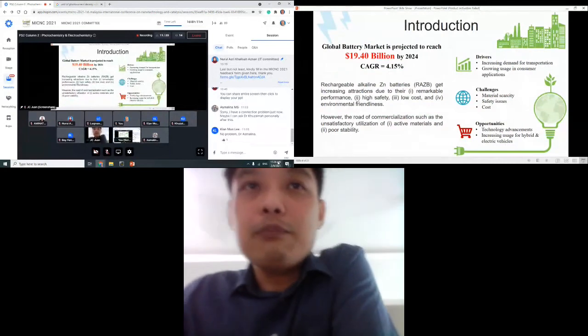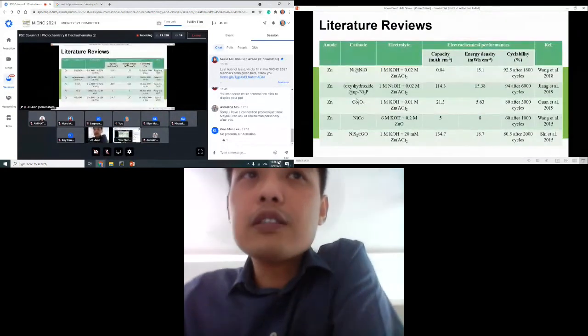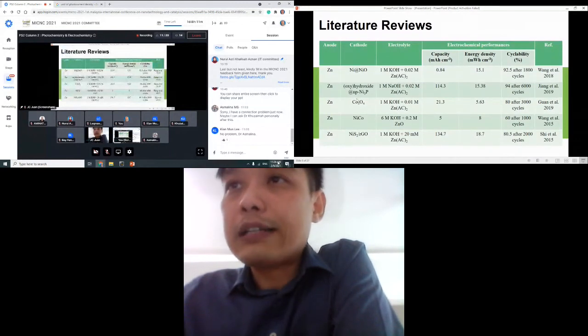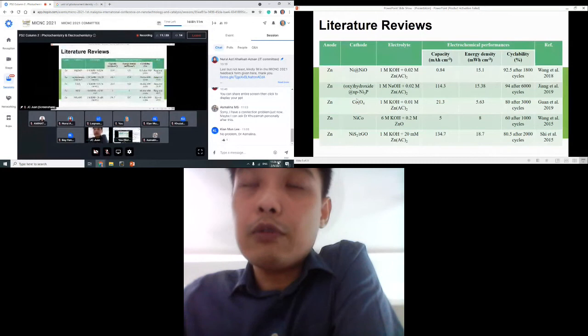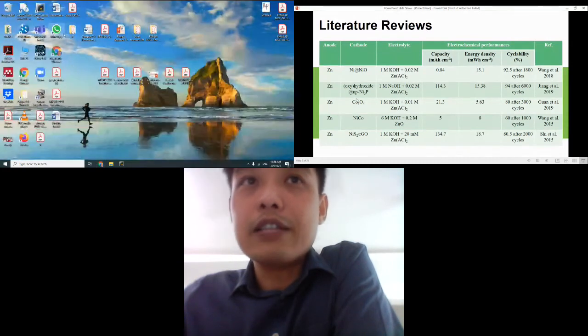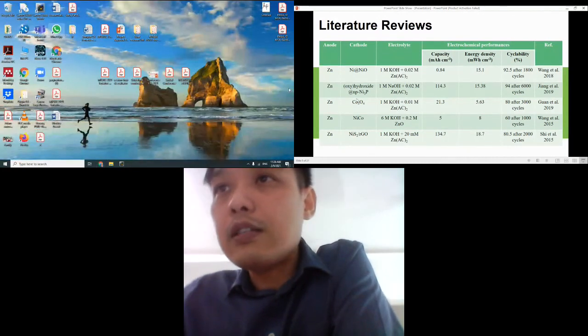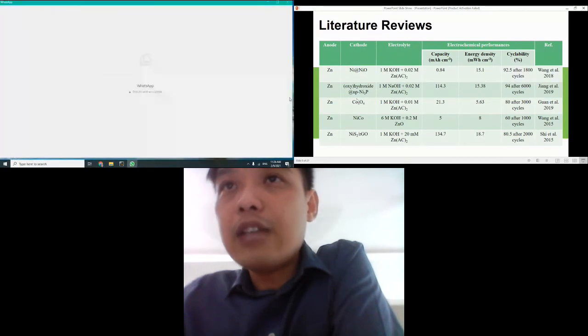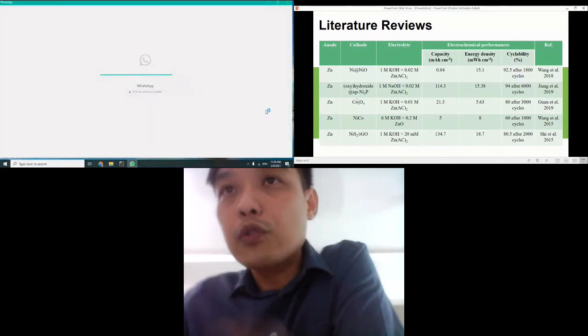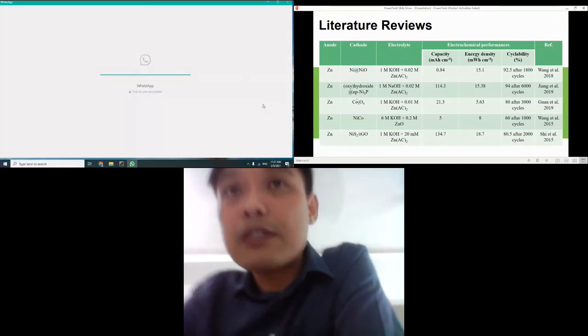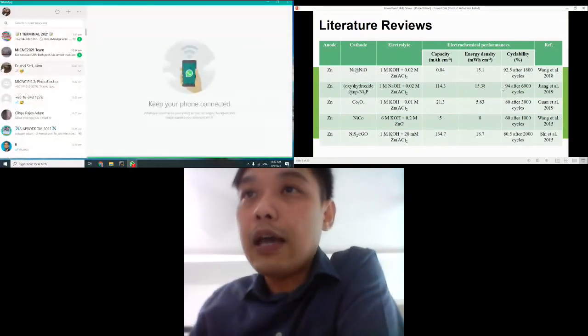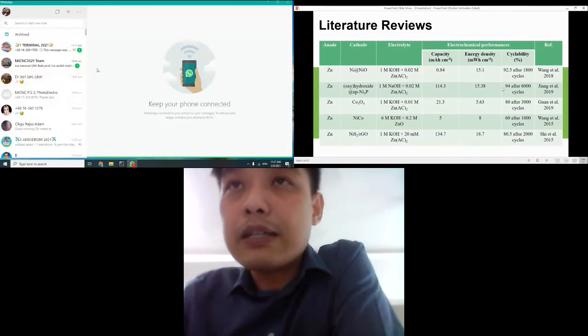So yeah, the rechargeable alkaline zinc battery is very important. So this is what we get from the literature. We can compare what the current trends are for this rechargeable alkaline zinc battery. Basically, you can see that the highest energy density can go up to 15.38, and the capacity is 114. The cycling is quite good, but again, the energy density and capacity are quite low in this sense. So there is room for improvement.